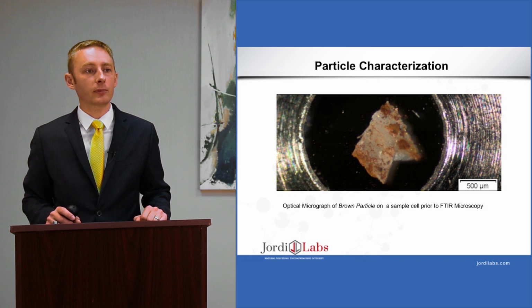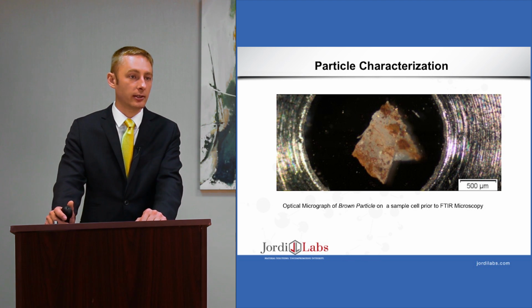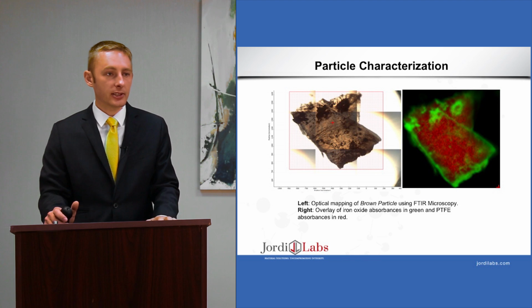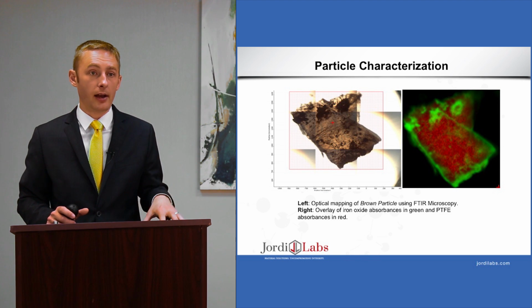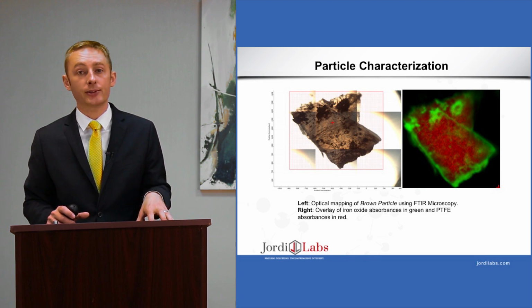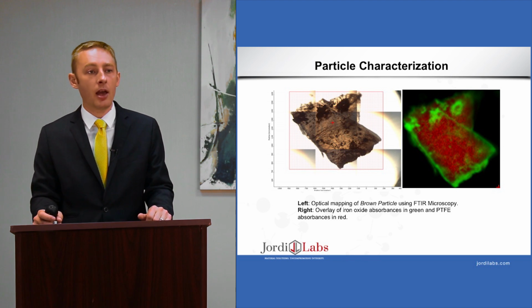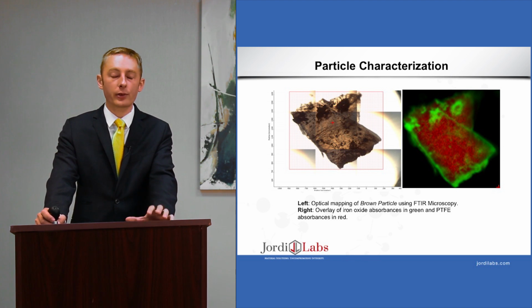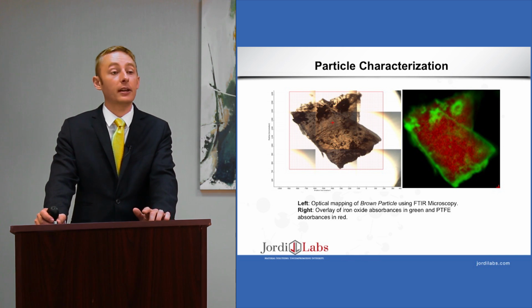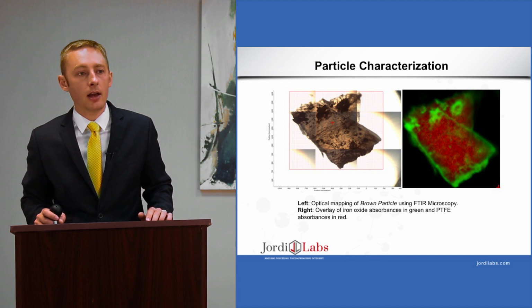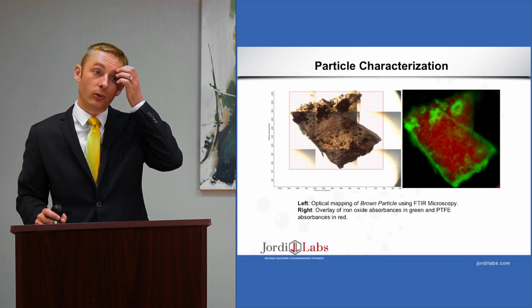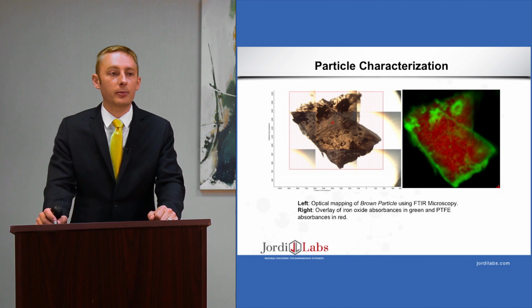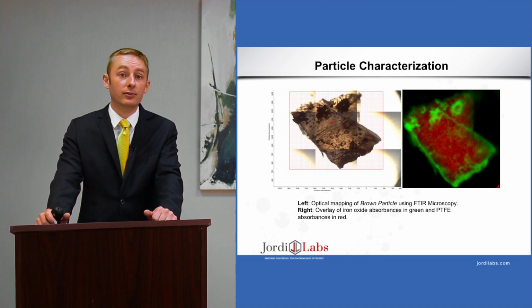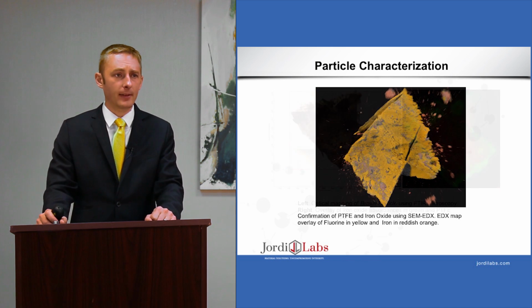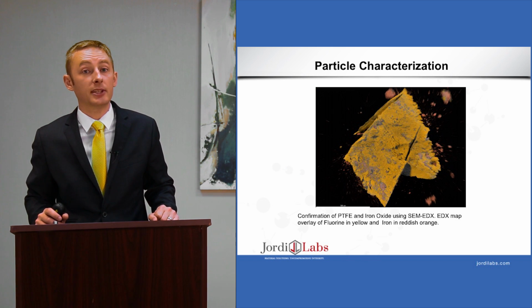We don't want to jump to conclusions, but I think we'll pretty conclusively show what it is in a little bit. So in this particular slide, on the left side, we have the optical micrograph that we've done at higher resolution, and we've mapped together all of the imaging. And on the right, we have an overlay of iron oxide in green, and also of PTFE signals, that's fluorinated ethylene absorbance, in red. And so we're starting to draw some conclusions from this. It looks like it's some PTFE with some iron oxide on it. And then what we did to follow up with that is some SEM-EDX.